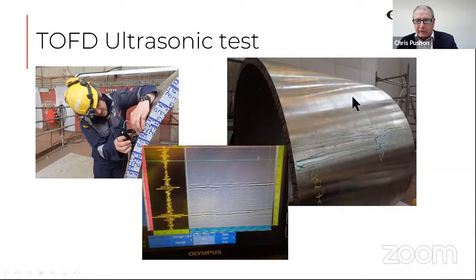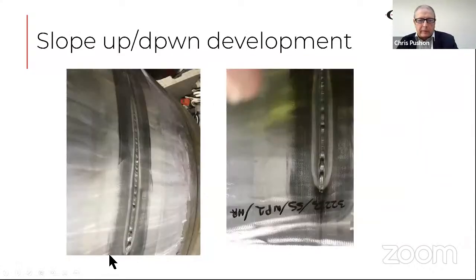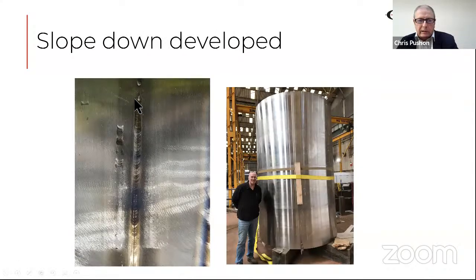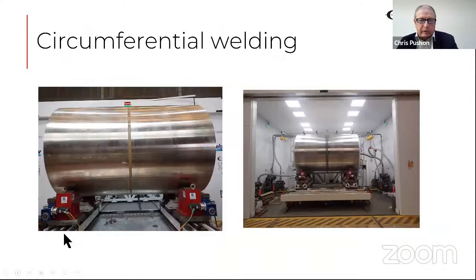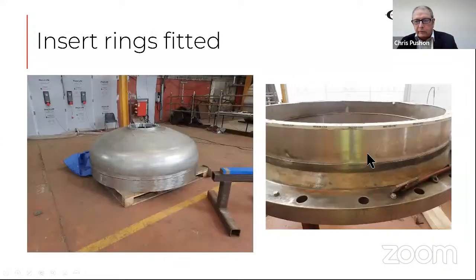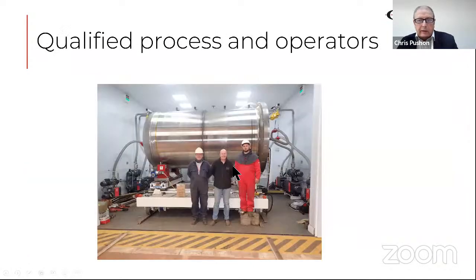So after circumferential welding, we carried out time of flight ultrasonic testing, and we then had to develop some systems for starting and stopping the weld, which worked quite well. So again, here you see for the circ welding, we have it in our white chamber, which is still white inside. And here you see the dished end and the flange connection. And at the end of it, we had a qualified father operator and son operator, with the son standing on a piece of wood so he can look taller than his father.